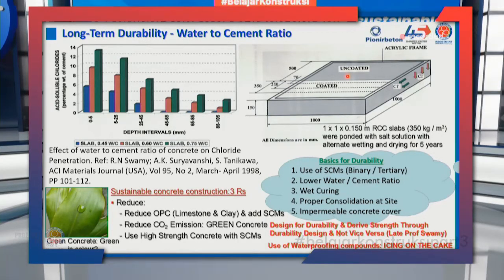After the end of the 5 years, we cored through these slabs. These slabs have 3 different water cement ratios, 0.45, 0.6, and 0.75. Now, after 5 years, we cored it and made slices. The slices were 0 to 5, 5 to 25, 25 to 45, and so on. All the slices at the same depth were mixed together and crushed together. Then you found out how much chloride has entered at different depths. So then this graph is plotted.